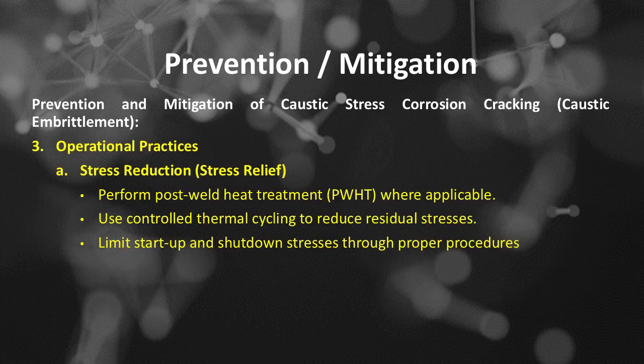Number 3 of prevention and mitigation of caustic stress corrosion cracking or caustic embrittlement is operational practices, which includes, number A, stress reduction or stress relief. Perform post-weld heat treatment, PWHT, where applicable, use controlled thermal cycling to reduce residual stresses, limit startup and shutdown stresses through proper procedures.